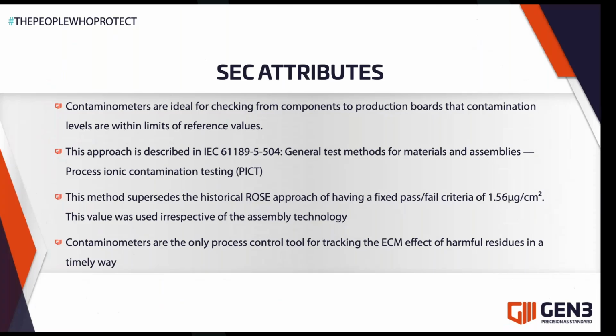So thank you, Chris. Ionic contamination testing, or contaminometers as ours are called, is ideal for checking from components to production boards that contamination levels are within limits of reference values. This approach is described in IEC 61189-5-504, the general test method for materials and assemblies, otherwise known as process ionic contamination testing. This method supersedes the historical Rose approach of having a fixed pass-fail criterion of 1.56 micrograms of sodium chloride. This value was used irrespective of the assembly technology. So ionic contamination testing is the only process control tool for tracking the ECM effects of harmful residues in a timely way. So what happens if I have a failure?